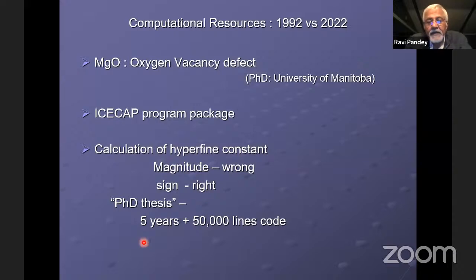So just the last slide, to give you an idea of what has happened in the last 40 years. When I was doing my PhD, I was looking at the oxygen vacancy defect in magnesium oxide. We wrote a program which is very long. It was 50,000 lines. It took about 5 years to do. And I was looking at the hyperfine constant, which is basically the interaction between the electron and the nuclei at this defect site. So when I did everything, I found that my sign is right, but the magnitude was totally wrong.